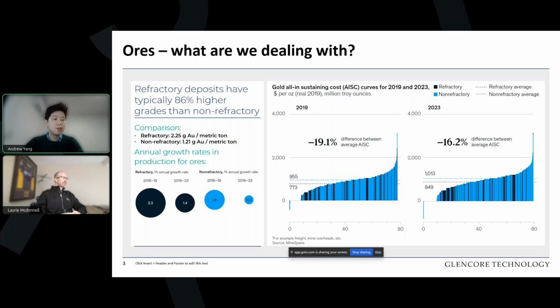Between 2015 and 2023, for the annual growth rate in the production of ores, we're seeing that the refractory deposits are starting to outpace the non-refractory ones, meaning that producers and sites are starting to recognize that there is this hidden value here, this locked value that should be unlocked, despite its additional processing steps.